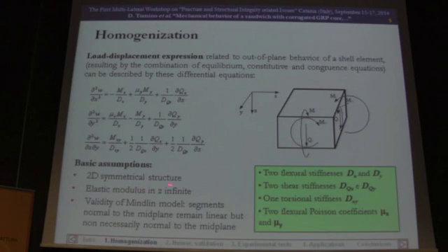The core is symmetrical with respect to the mid-surface of the sandwich, and the elastic modulus in the out-of-plane direction is infinite. This means that you cannot assume that indentation or deformation in the thickness direction is present. And the Mindlin model links the shear deformation to the deformation of the mid plane.